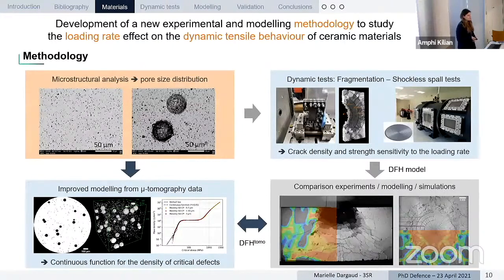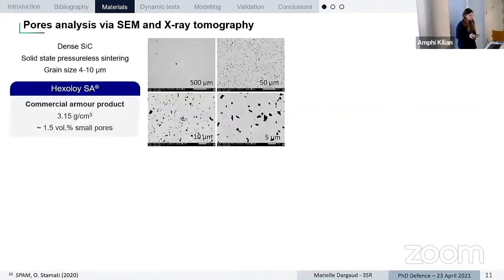So first, for the microstructure part. In this work, I'm going to present the results for two materials, which are two dense silicon carbides made from solid-state pressureless sintering. The first one is the material called Hexoloy SA, which is a commercial armor product of the company Saint-Gobain. And this material presents a low amount of porosity. Here you have some SEM images at different scales showing these porosities, sintering pores at the boundary of the defects.